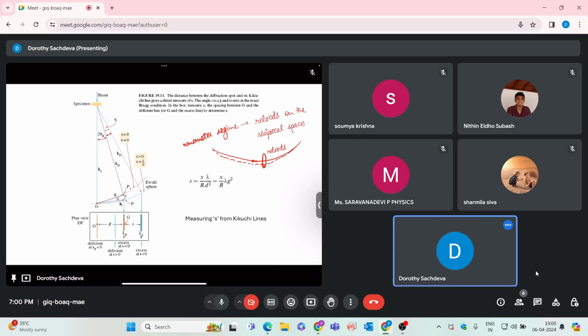So in reality, these are not single spots, rather they are these railroads. So even if the Ewald sphere is not completely touching the center of this direct spot, that will give you the diffraction, because this is not one single spot, rather it is a railroad, and there will be much more region in which the Ewald sphere can touch this railroad to get the diffraction beam.